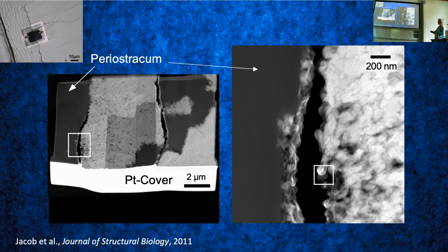But nevertheless, we have a piece of the shell here, which is calcium carbonate. You can probably just see the granular texture. It's a bit closer here. This is then our area where we focused, and we actually could use that funny crack that happened as an artifact, really, to zoom in on an area where we were really interested. So you have this granular structure that we've seen in the SEM images. This is the crack right here. On the left side is what is not so interesting for us, that outer layer of the shell. And we're zooming in into this little area where we have several of these granules sitting.